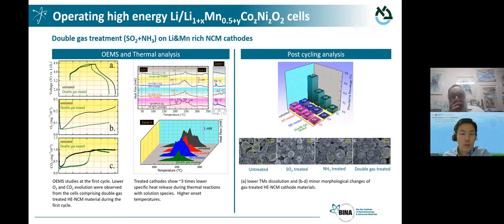So here in this slide, and I may apologize for the very busy slide that I'm showing, but since this is a special niche event, a special opportunity, I thought to share with you as much information as possible, and people who can read fast can digest the information, which hopefully may be important. So here we have four channels of information. First of all, we measure online gas formation. We measure CO2 and oxygen evolution. And we see for sure that with the treated materials, we mitigate the gas evolution.